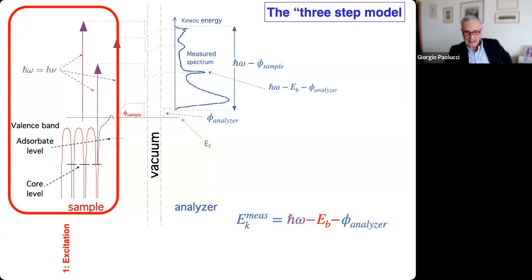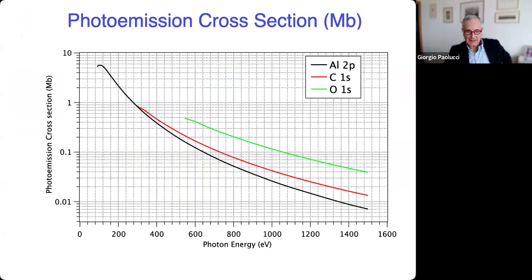For example, if you look at these levels, so you took the aluminum 2p, the carbon 1s, the oxygen 1s. This is the way they behave. You see that overall the photoemission cross-section decreases as the energy increases, which is one of the reasons why I said that you normally prefer to work at low energy.